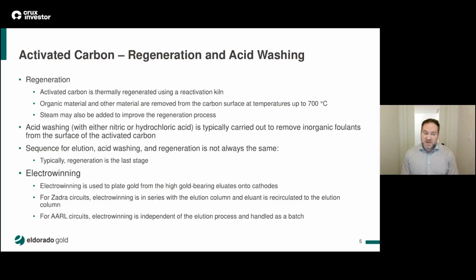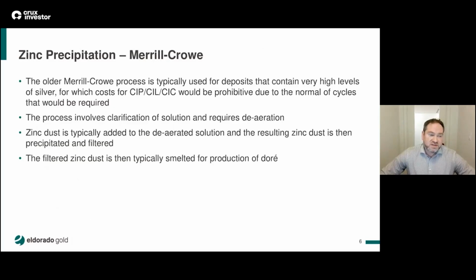And for Zadra circuits, it's done in series, with the elution column and eluate recirculated to the elution column during the process. And for the AARL circuits, it's typically more handled as a batch, as it's independent of the elution process. While most gold is recovered to activated carbon, some gold is actually recovered in solution by the Merrill-Crowe precipitation.